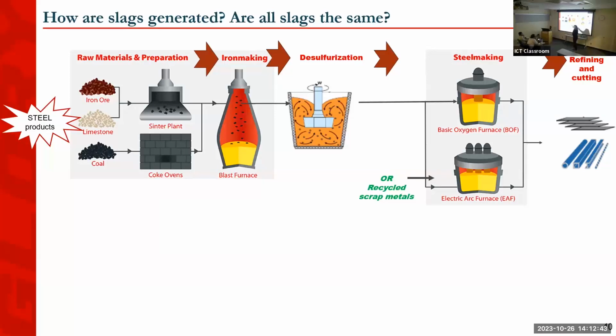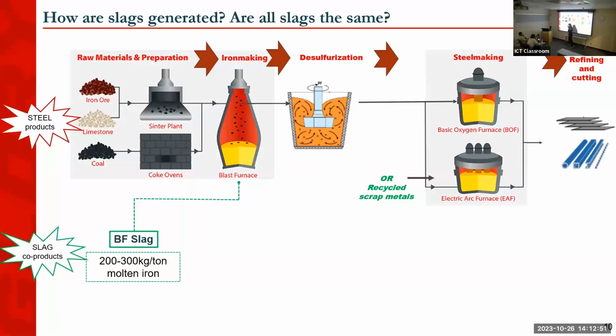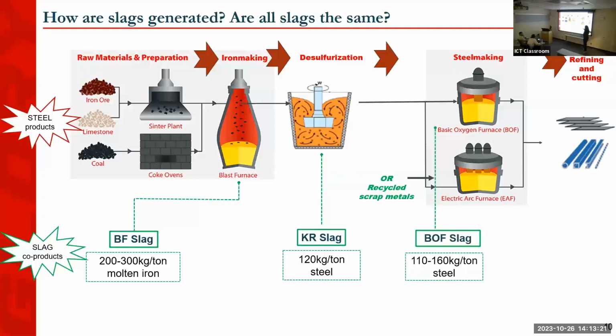In each of these processes, we have different slags being generated. From the blast furnace, we have the first type of slag, which is called blast furnace slag, or sometimes iron slag, because it's generated during the production of molten iron. About 200 to 300 kilograms per ton of molten iron are generated. From the Kanbara reactor process, we have about 120 kilograms per ton of steel of this slag being generated. From the basic oxygen furnace, we have the BOF slag, and from the electric arc furnace, we have the EAF slag. So it's really important to understand that in each of those parts of the steelmaking process, we have different slags.